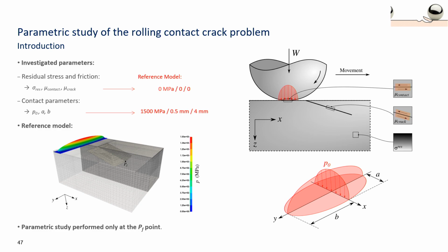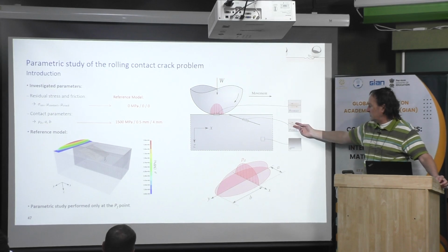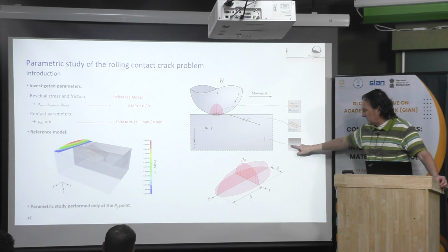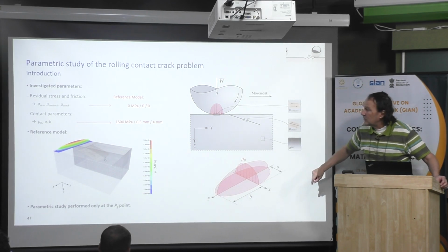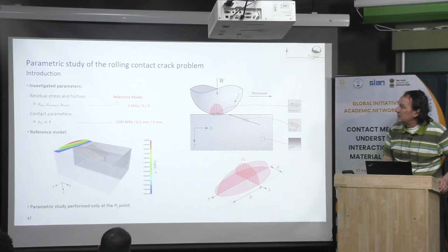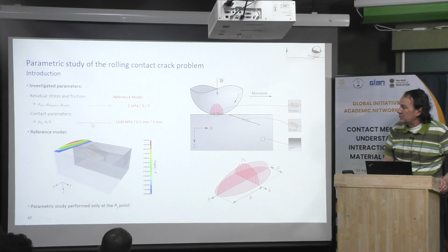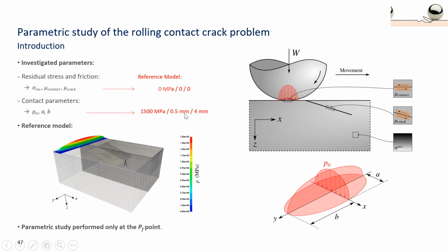Okay, then now a parametric study just to have some results. There is a friction at the contact that we can consider, the friction coefficient between the crack faces. We can consider the residual stresses within the body. The reference model is without residual stresses, without friction force at the contact, without friction force between the crack faces. And the contact parameters: the load is 1.5 gigapascal for the Hertzian pressure, 0.5 millimeter for the semi-minor axis of the elliptical contact in the rolling direction, and 4 millimeter for B, the major semi-axis in the transverse direction. This is then the reference situation.